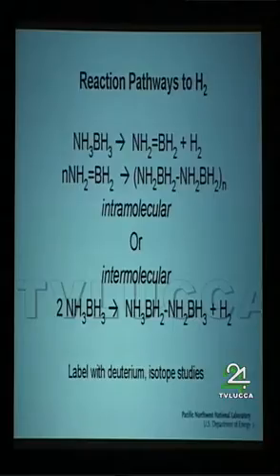or intermolecular pathway. But there were lots of experiments designed where they tried to trap the aminoborane, this double-bonded olefin species right here, and they were never able to trap it, so they said that it was very reactive, and so you couldn't trap the thing. But alternatively, you never make it because it goes by an alternative mechanism. And there is one paper that discusses back in the 60s about bimolecular pathways for hydrogen release.